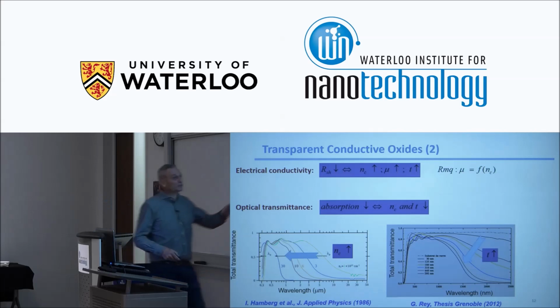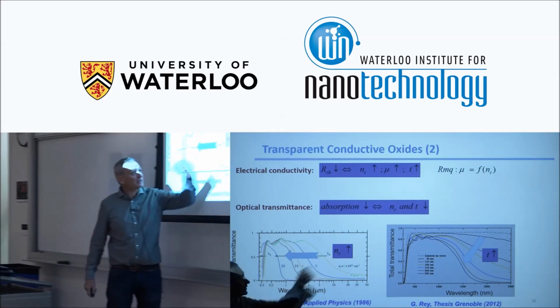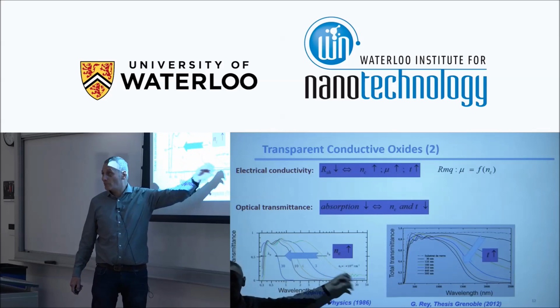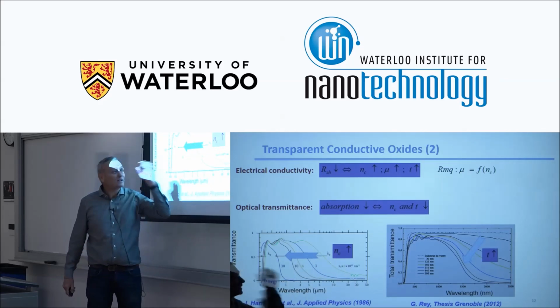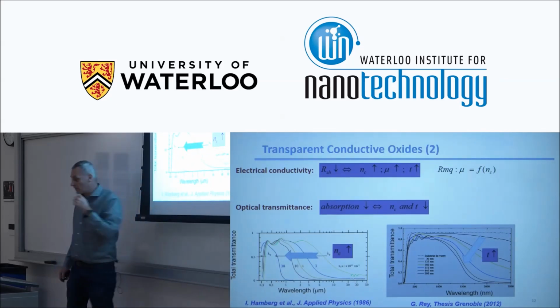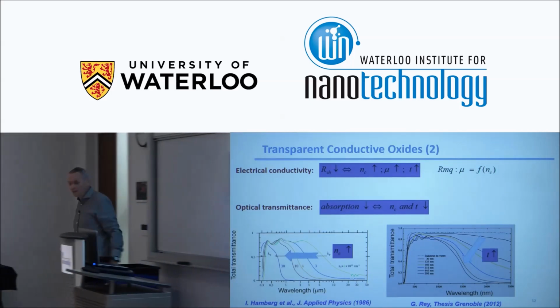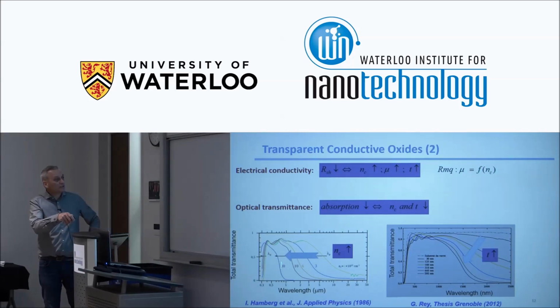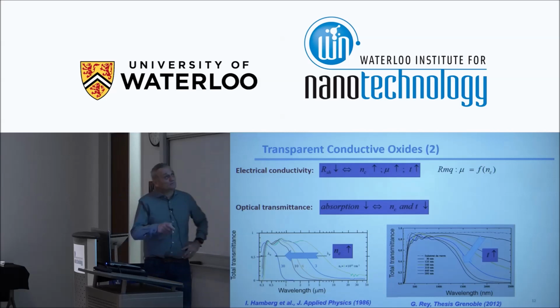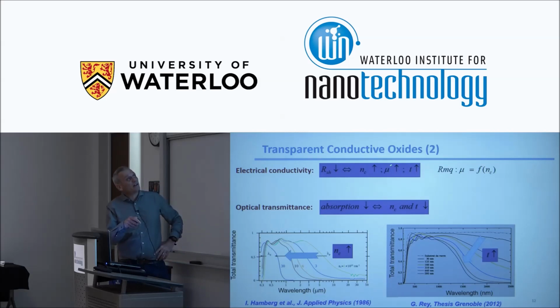We have total transmittance versus the wavelength. If we increase the carrier density, we are going to increase the plasmonic absorption. That means the window within which a transparent electrode is still transparent is going to be narrower and narrower, especially in the near infrared, but you can reach a bit of the visible part as well. And it's the same for the thickness of the layer, the total transparency versus the wavelength. When you increase the thickness, we start to be less transparent. So the problem is that NC should be high to have good electrical resistance and low to have good optical properties, the same for the thickness, so it's a kind of compromise.